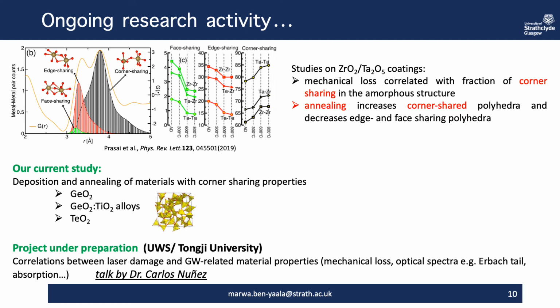So concerning the ongoing activities, we are currently investigating materials with corner sharing properties, including germanium oxide, but also germania titanium alloys, where the titanium will be used to increase the germania refractive index, and a third material, the tellurium oxide. And this is based on the findings published by Prasai while studying the zirconia doped tantala films, where he showed that the mechanical loss is correlated to the fraction of corner sharing in the amorphous structure, and also that annealing increases this corner shared polyhedra and decreases the edge and face sharing polyhedra.